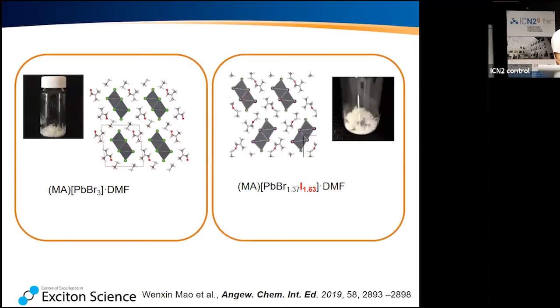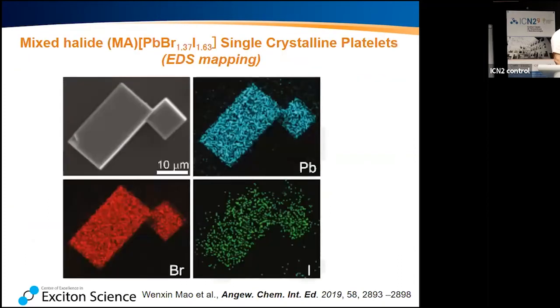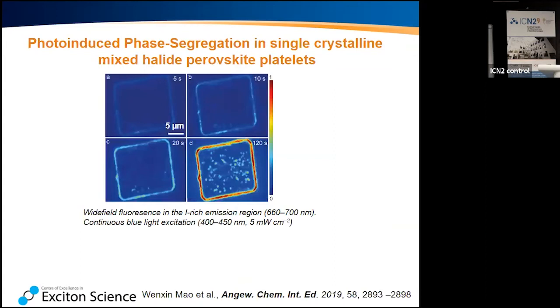The only thing we had to do is make our same precursor, but not with a pure bromide, but a mixture of bromide and iodide, and make these mixed halide platelets. And here's an example of that with EDS mapping to show it's homogeneous. And let's see whether we get lucky a second time.